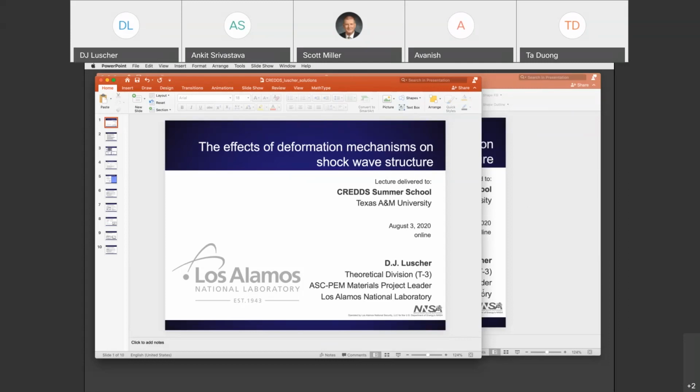And if you apply a pressure to a shell, you're going to generate a three-dimensional state of stress within the shell, and that's going to include tension because of plate or shell bending, right? So if you apply a pressure to the window, you're going to create tension on the opposite side, and at these levels of pressure, that'll just fracture the glass, and then the glass is carried downstream in the moving fluid flow of the pressure wave that's continuing on. So I hope that answers that question, and it does seem like it's relevant to the discussion on shock waves.